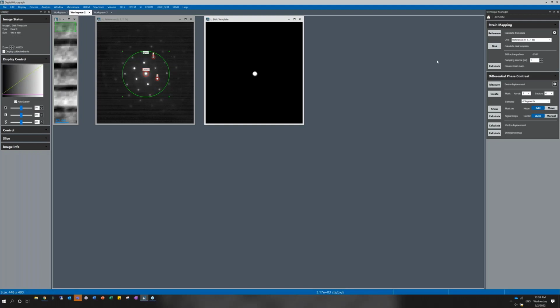And I am now ready to move to the next step, which is first, I can define a diffraction pattern rotation angle. This is because in many cases, as it is here, there is a rotation angle between the diffraction image and the real space scanning dimensions. The software calculates the strain in the X and Y directions of the diffraction image. So to make easier sense of what is what, you can have the software rotate those vectors and give you the correct numbers in the directions for your real space image. Here, I have a negative 25 degrees rotation. So I go to the setup box and enter that negative 25 degrees for the software to use.